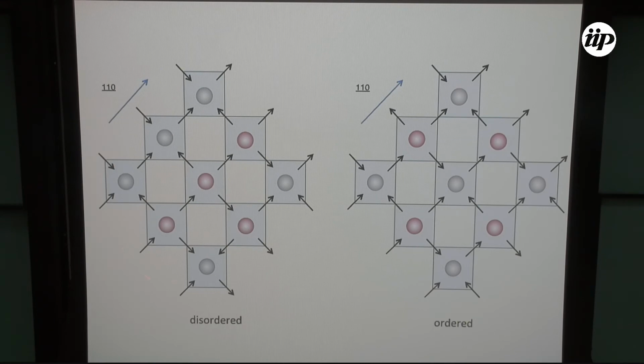As I told you, what the ground state is when you put this field is just this disordered soup of single charges. But now, let's say you want to flip one of these spins. I'm comparing the case where the system is completely disordered with the case where the system is ordered in this way I told you. For this state, you see that one blue charge has all red charges around. So this is the case that will give you a rho staggered equal 1. Let's say I flip that spin. In one case, I'm creating a double charge here and a neutral site here, while in the other case, I'm creating two double charges.